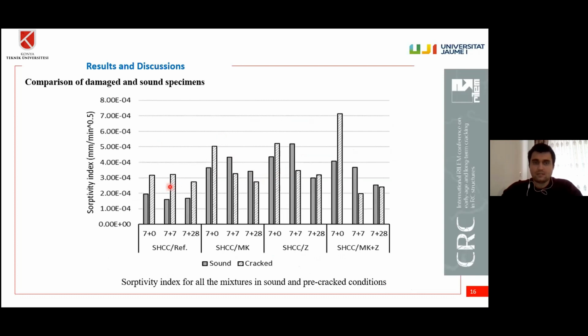To be more precise, you can also see both comparisons. For example, the gray belongs to sound, and the shattered gray chart belongs to cracked specimens. As you can see, the sound specimens are lower than their preloaded counterparts, as expected. But you can see that the reference specimens showed no change during the further curing ages, while the mineral admixture bearing specimens showed lower sorptivity index compared to their preloaded specimens, especially beyond 7 days. You can see this in these two bar charts. And this was very pronounced for the metakaolin and zeolite bearing specimens.